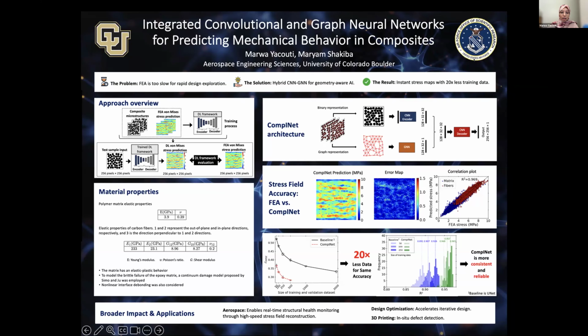That's where I introduce CompiNet, the Composite Integrated Network. Most existing AI models look at a composite microstructure as if it's just a black and white image. Fiber here, resin there. But in composites, location alone isn't enough. Failure is driven by how fibers interact, their spacing, clustering, and how well they bond to the surrounding materials. CompiNet incorporates physical intuition directly into its design.